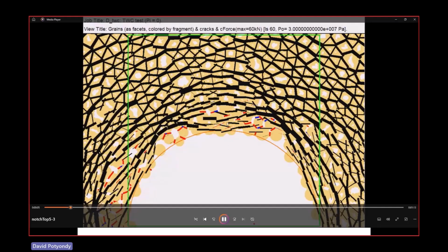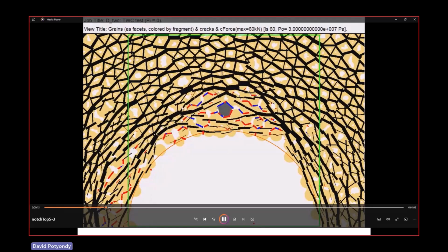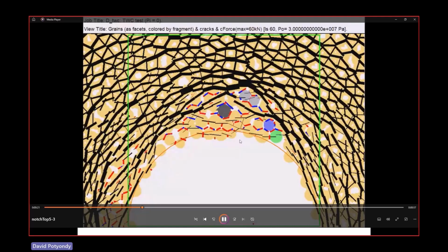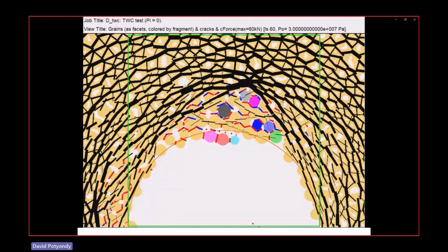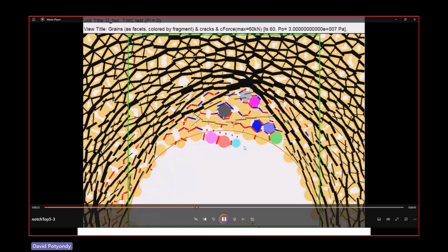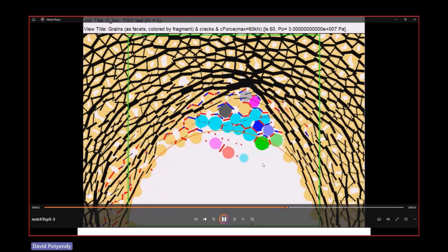If we watch this, as it starts to break, watch the force chains rearrange in response. Look at how it's forming this very high compression region at the tip. As more damage occurs, there's almost no load being carried in this broken material anymore. And again, this is the mechanism for why you get these borehole breakouts. Borehole breakouts also have this tendency to form surface-aligned fractures and fragments, and that's what we're seeing here. Notice at this point, this is almost fully formed, and now we've got this big compression region at the tip of that notch, which is shutting down the process. Obviously, if we increase the load a little more, this thing can grow. Eventually, these things fail in a very interesting way.